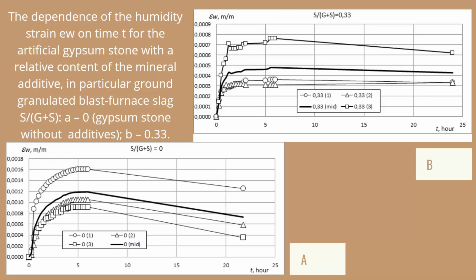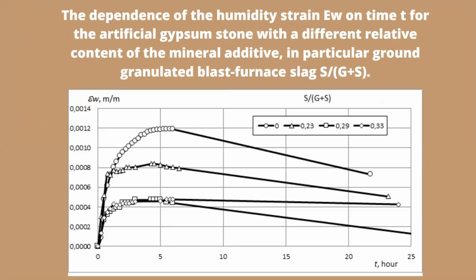It can be seen in picture 3 that the value of humidity strain depends on the content of the mineral additive, granulated milled blast furnace slag. A maximum strain is observed for the gypsum stone without mineral additive. A relative strain decreases with an increase in the slag content. However, this decrease has no linear character. It is by analogy to the dependencies of the strength and water resistance on the slag content.